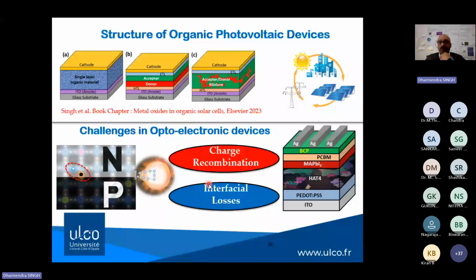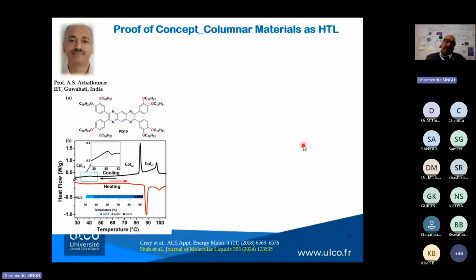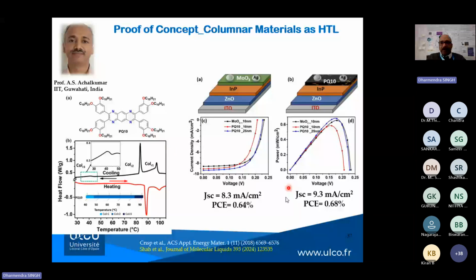So now we thought, why not use these columnar materials at the interface, because these materials compel charge carriers to move along one dimensional direction. So before directly going to the fabrication of devices, we thought to do a proof of concept. So we contacted our colleague Professor A.S. Achalkumar at IIT Guwahati to make a particular columnar material that is shown here, the short name is PQ10, and we characterized it. And then we took one reference parent device that was reported by the group of Crup in ACS Applied Energy Materials.